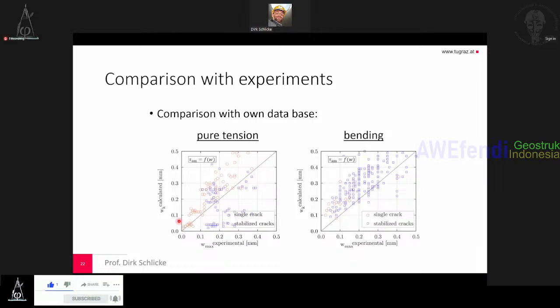But there is some confusion with the effective concrete area, and I calculated with the small concrete area from the Eurocode definition. But if you use the entire concrete area all the time, also in the stabilized crack stage, then it would also shift over this. Maybe this is, I don't know if you can understand it by this. This probably needs a bit more discussion. But actually for single crack stage, this works quite well, as you see. For stabilized crack stage and pure tension, you must change.